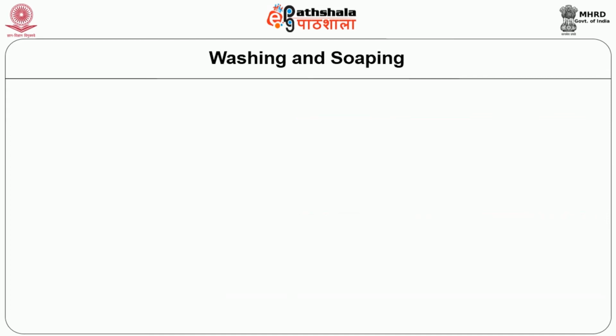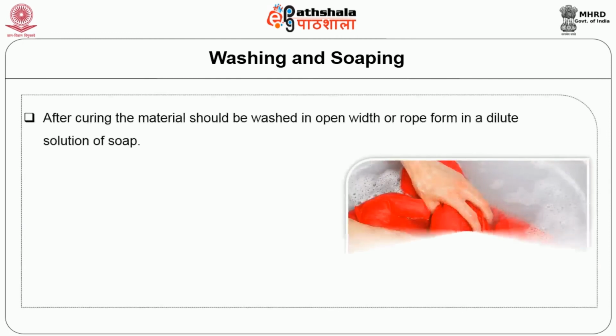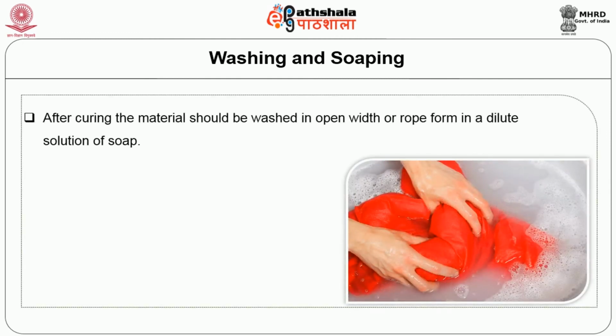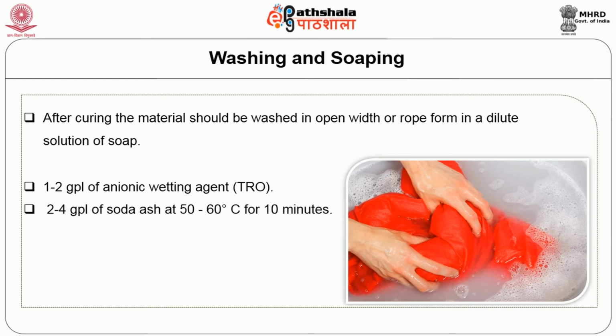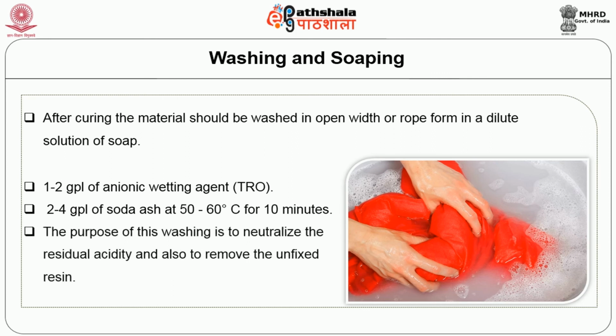Washing and soaping. After curing, the material should be washed in open width or rope form in a dilute solution of soap and 1 to 2 gram per liter of anionic wetting agent like TRO and 2 to 4 gram per liter of soda ash at 50 to 60 degrees centigrade for 10 minutes. The purpose of this washing is to neutralize the residual acidity and also to remove the unfixed resin.